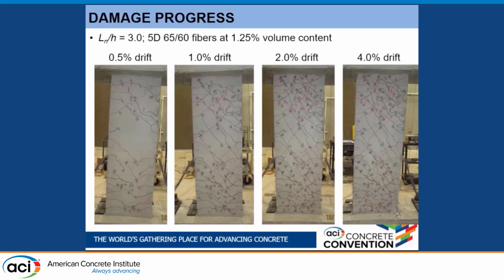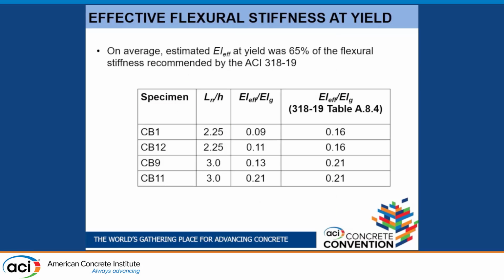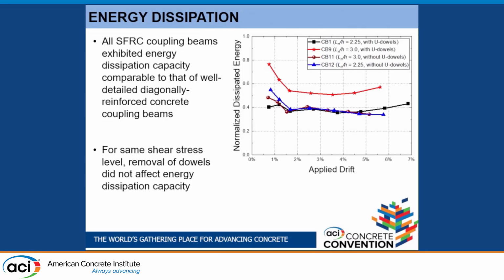At larger drift, we had quite a bit of damage at both ends of the coupling beam. In terms of effective stiffness at first yield, which you can use for an elastic analysis, since we don't have diagonal reinforcement here, our effective stiffness is about 2/3 on average of the effective stiffness recommended in Appendix A of the ACI code.